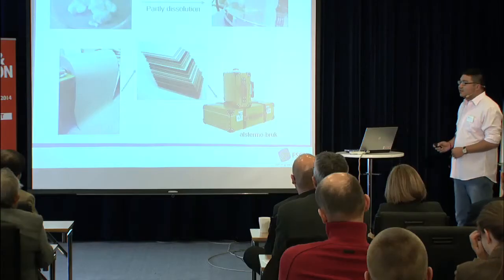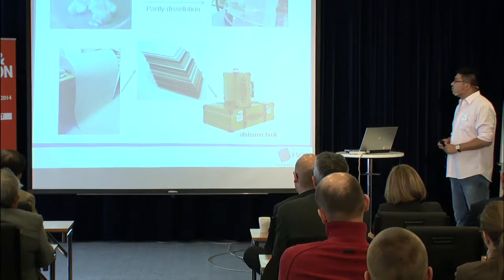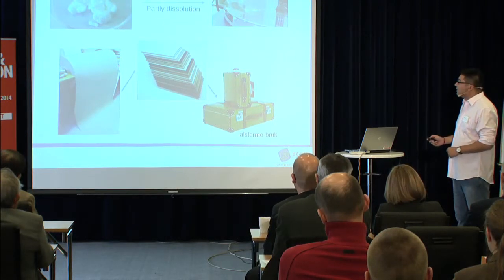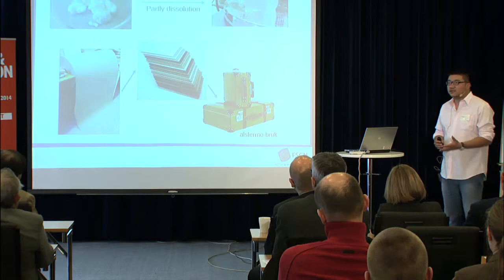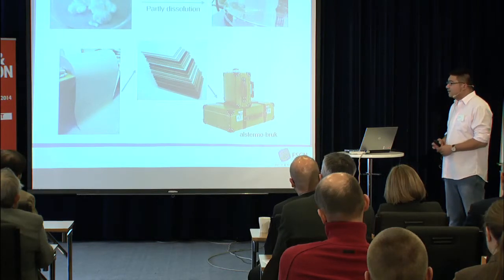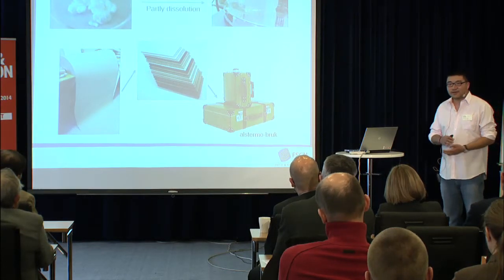And our aim is not total dissolution, since that needs a lot of effort. So partial dissolution is what we aim for. And what can we use the partly dissolved cellulose for? We think we can use it to modify the paper surface. Because if we treat the paper surface, dissolve the cellulose on the surface and regenerate it, it can change the surface morphologies. So we have the starting material as a liner board.